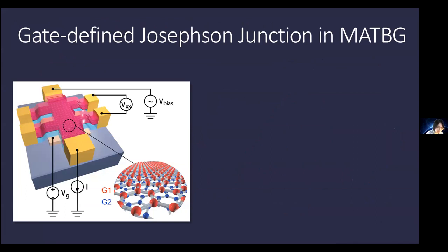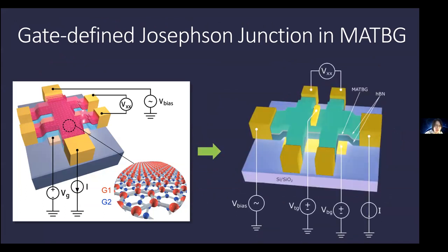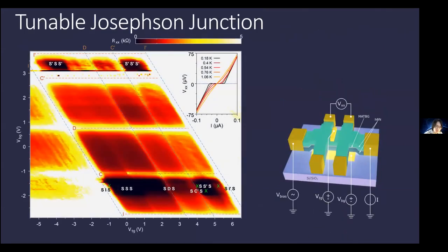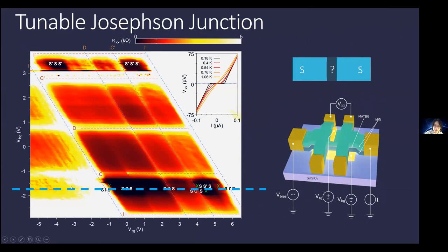In order to see this experimentally, in our typical device, we put a narrow top gate on top of it so that we can independently gate the middle region of this device. We can use this to achieve a Josephson junction. The transport in such a device is quite complicated because there are multiple PN junctions when you have 3 gates. Basically the bottom gate controls the phase of the entire device, which we can tune into the superconductor by setting the bottom gate voltage here.